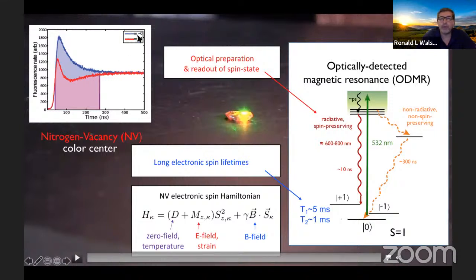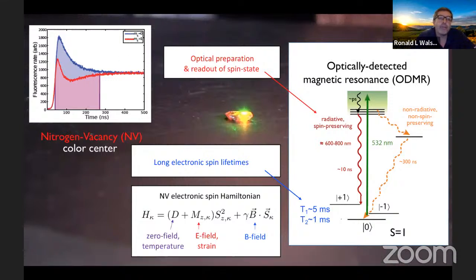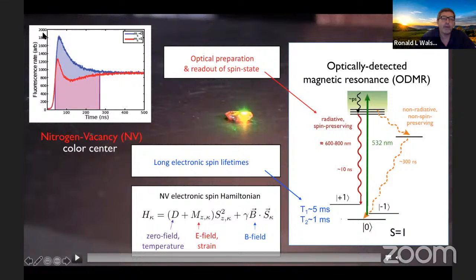In blue is when the NV begins in the m=0 state. And you turn on the green laser, and then monitor the rate of red fluorescence. As you'll see here, over a few tens of nanoseconds, the rate of fluorescence on average jumps up, reaches a peak, and then, depending upon the stochastic nature of fluorescence and the timescales of that, over a course of a few hundred nanoseconds, you reach a kind of steady state population between the ground and excited states, depending upon the intensity of the green light, and you get a steady state red fluorescence. So there's this spike in red fluorescence, and then you reach a steady state for the blue, which is starting with ms equals 0.